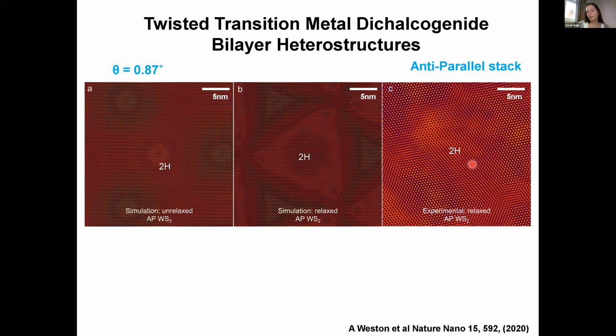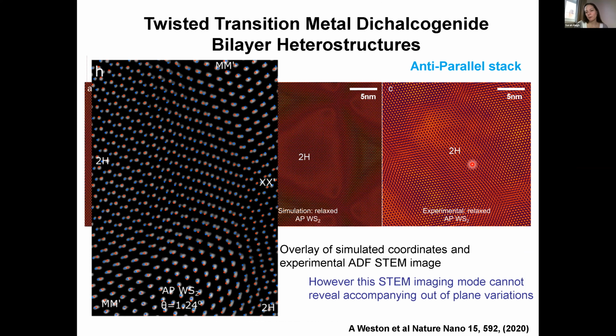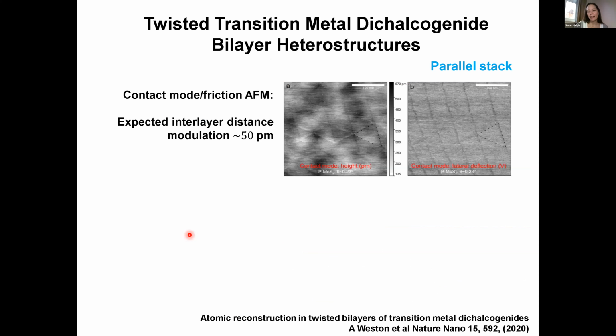So when we zoom in, we've overlaid the experimental data in black and white with the theoretical prediction, which is in red and blue. And you can see there's a really good match between those two. However, the scanning transmission electron microscope here hasn't got the sensitivity to show the out of plane separation. And we know that these different stackings do have differences in the interlayer separation of the order of about 50 picometers.